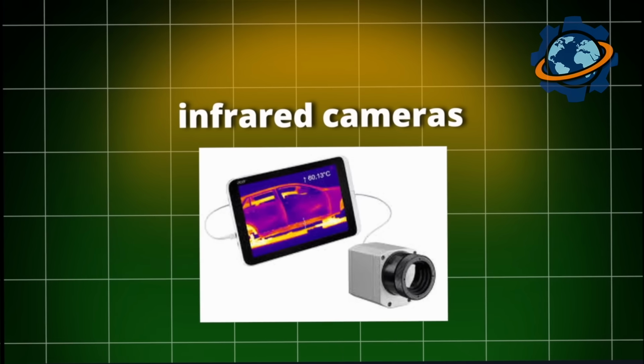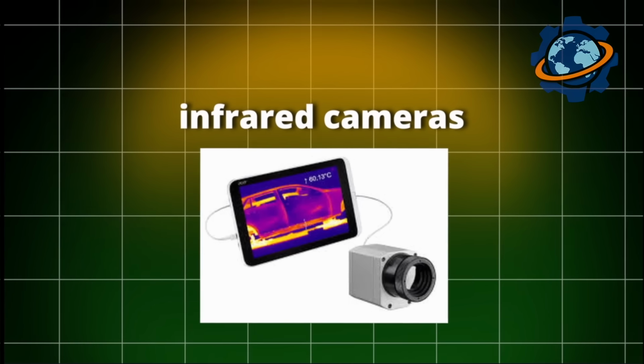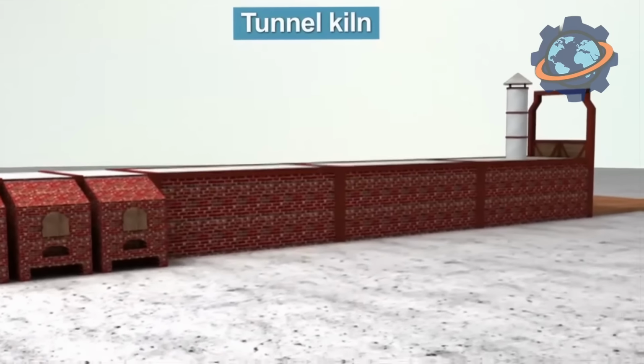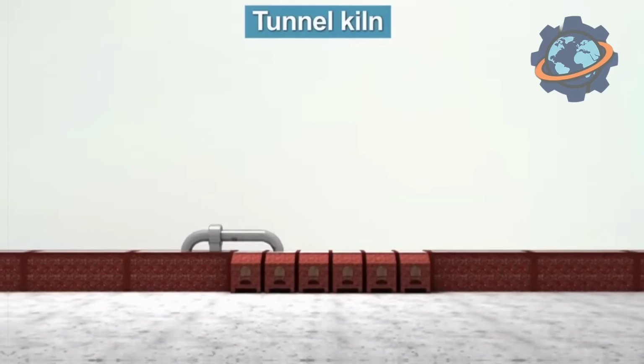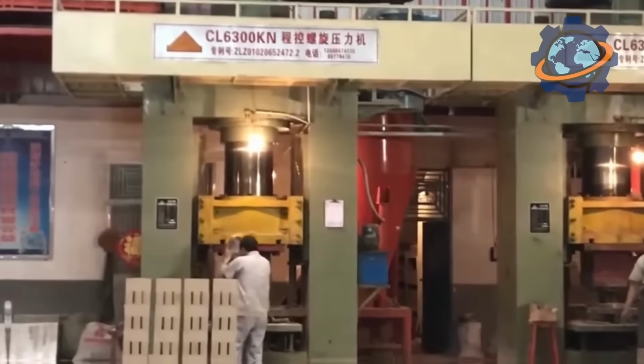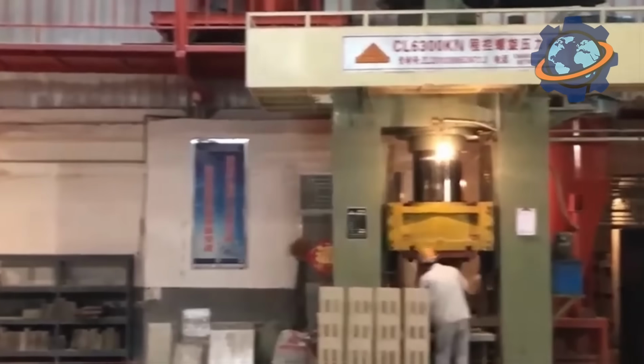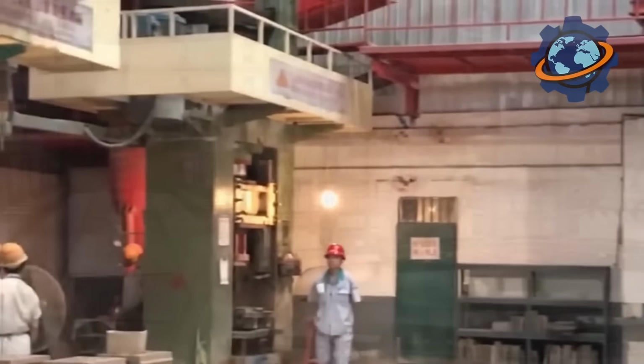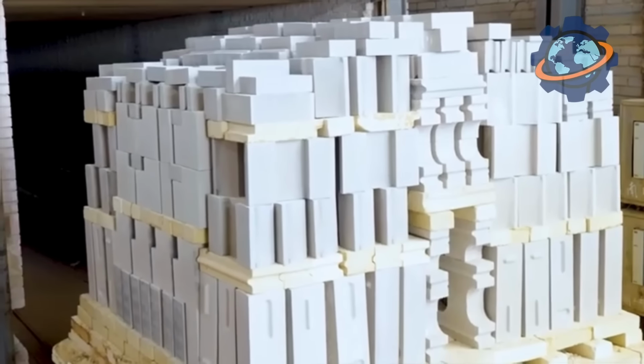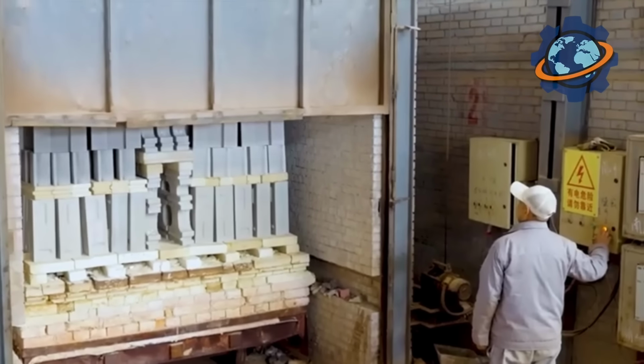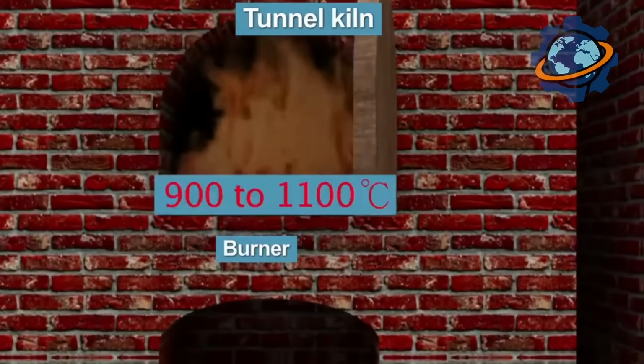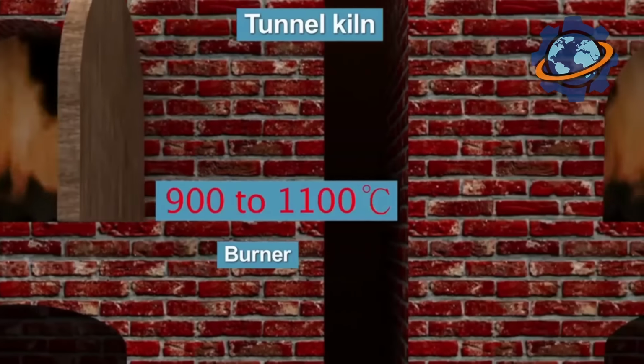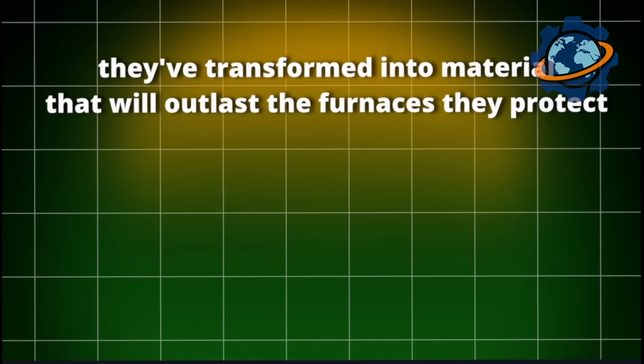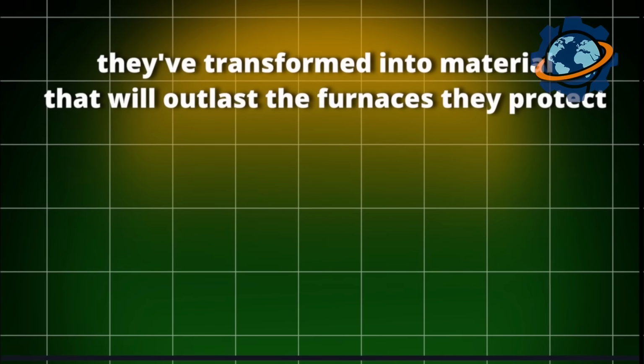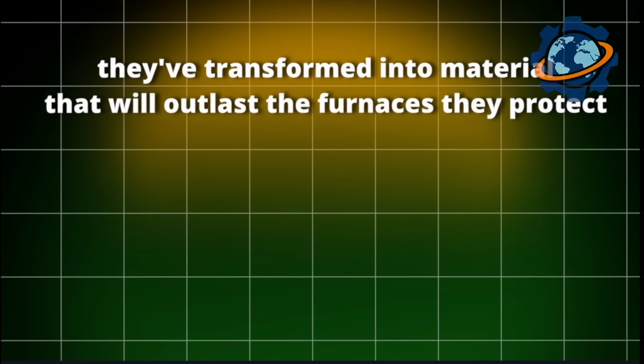But infrared cameras reveal the transformation. The bricks glow yellow, then white. At peak temperature, individual clay particles fuse into dense ceramic matrix. The chamote, already fired once, provides dimensional stability, preventing the shrinkage that would crack ordinary clay. When bricks finally exit, they've transformed into material that will outlast the furnaces they protect.